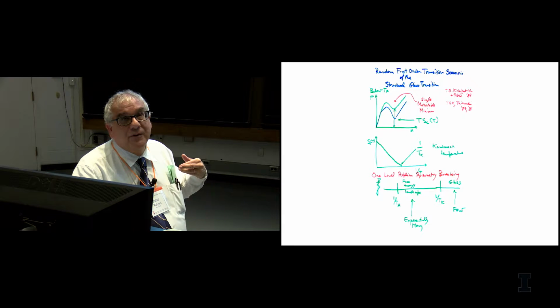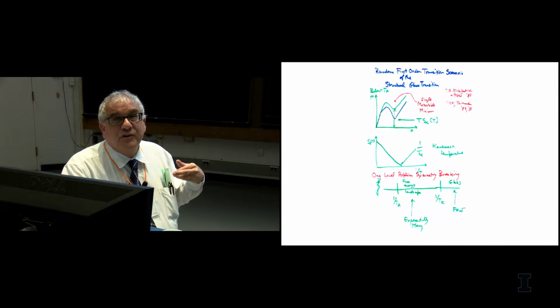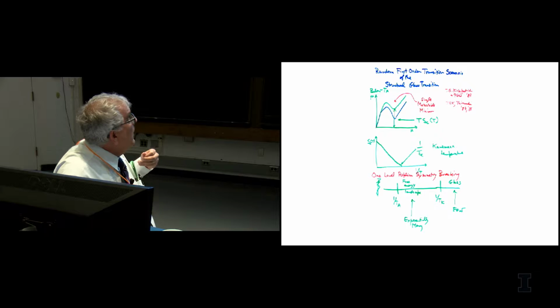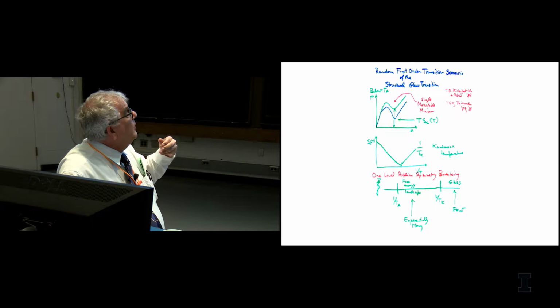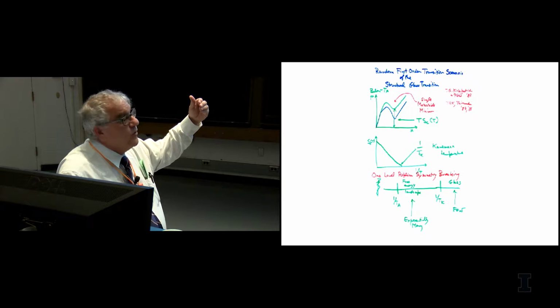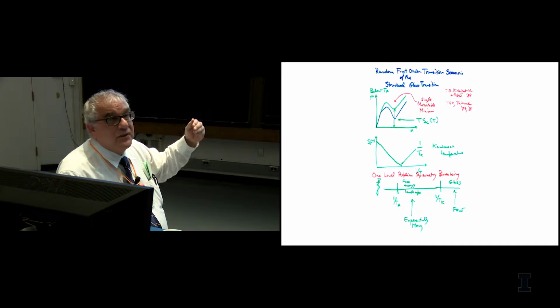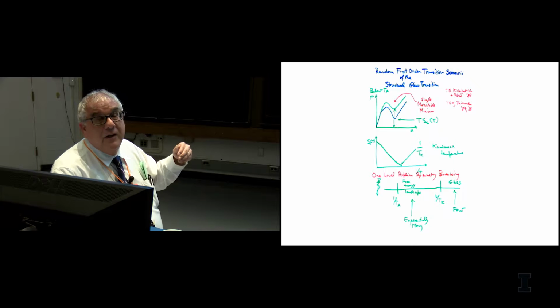Their viscosity is about 100 times that of water. And what happens is that as you cool below that, you now start to see a very strong dependence of the timescales on the temperature.